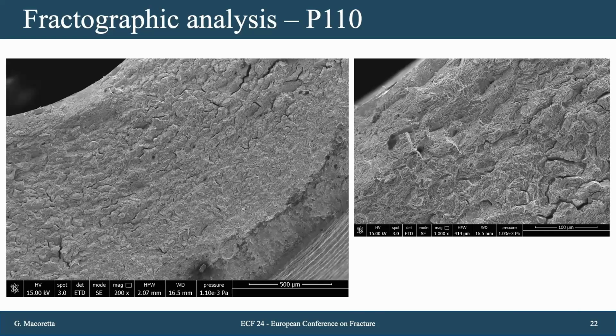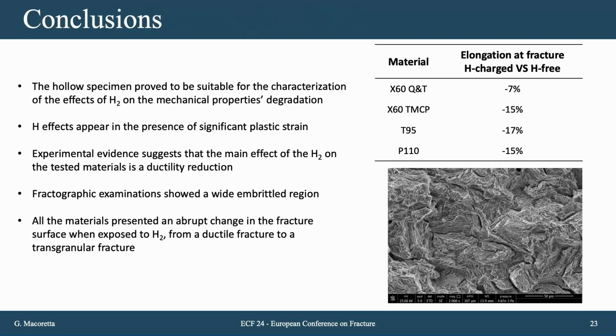You can see here, in another portion of the same specimen, how the hydrogen-affected region reached the outer part of the specimen, and then we have only the final shear lip with some smearing traces due to the final fracture. Just to conclude, we observed that the hollow specimen configuration proved to be suitable for the characterization of the effect of gaseous hydrogen on pipeline and casing steels.